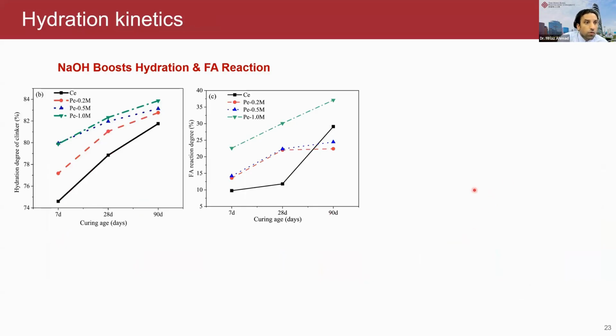So here we studied the hydration properties of the cement. You can see that the green and also the blue have a very high hydration degree. It means more cement is reacting. Also, if you see here, a greater amount of the fly ash is reacting when we use this approach.